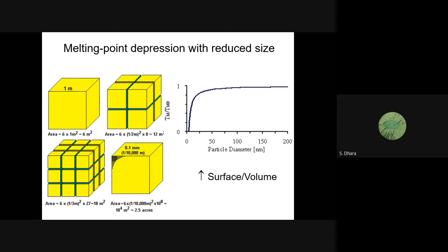If you deal with gold, normally the melting point will be how much? More than 1000 degrees centigrade, or close to 1000 degrees centigrade, or more than that, I don't know. But it goes down to 200, 300 degrees centigrade. You can melt them, at least the surface, and do a lot of physics or nanostructure growth on that. So the reason was easily understood.